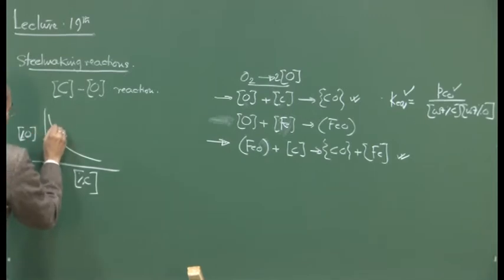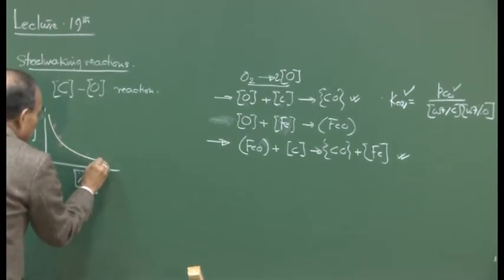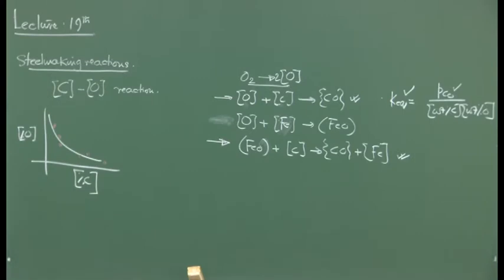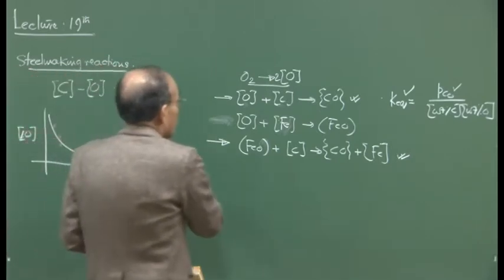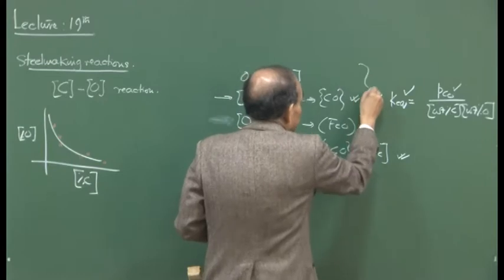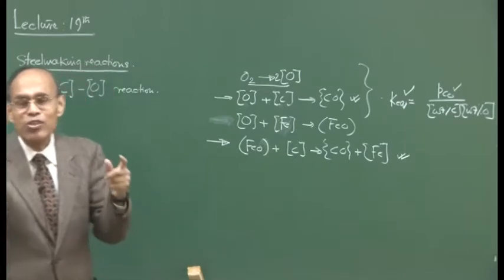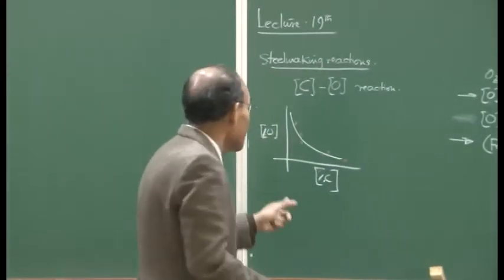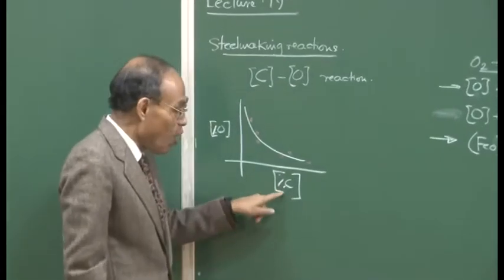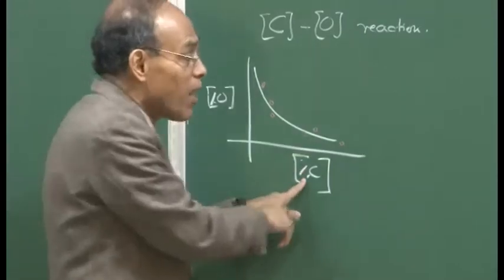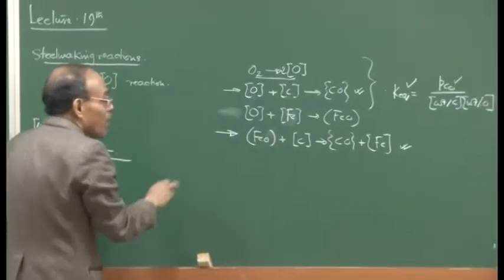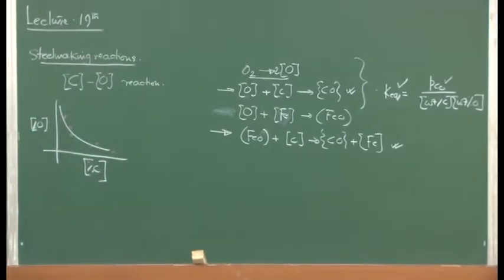And as I have indicated, experimental observations indicate that the carbon-oxygen reaction really operates close to equilibrium. Now, this essentially indicates that if this is true, then both these reactions are operating close to equilibrium. Because this is a slag metal reaction, if I also say that there is not only gas metal equilibrium, but there is also slag metal equilibrium, then for this much concentration of carbon in the system, this particular chemical reaction will also be in equilibrium, and the activity of iron oxide in the slag is going to be fixed.